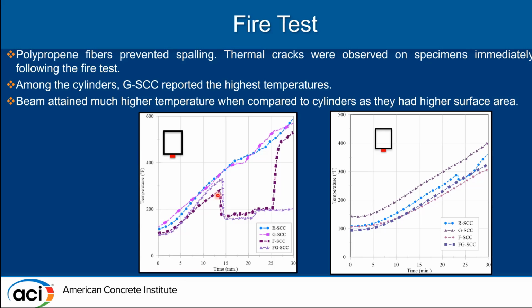Similar results were observed, that no spalling was observed for the specimens, except for few damages to the edges of the beams. And the conclusion of the fire test was that the glass pozzolan basically acted as a thermal conductor. And previous research shows that it tends to act as a thermal insulator. However, the exact opposite was observed in this research.